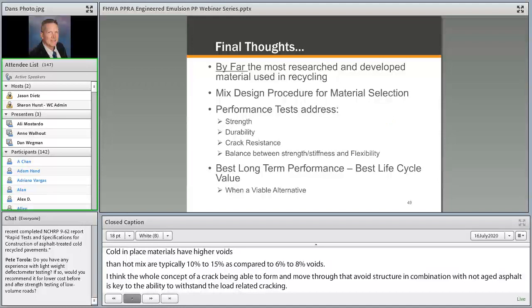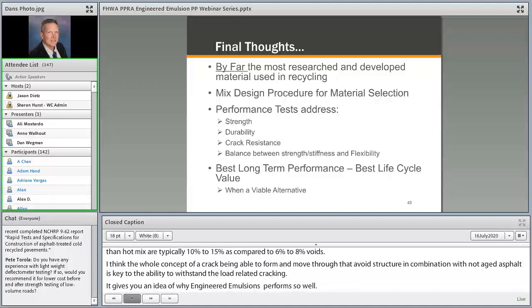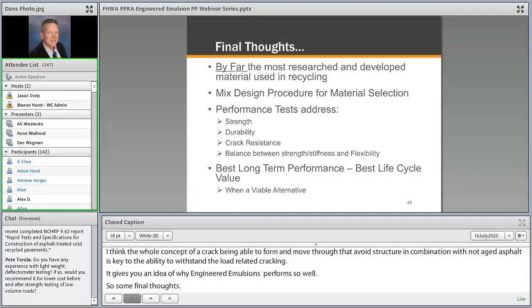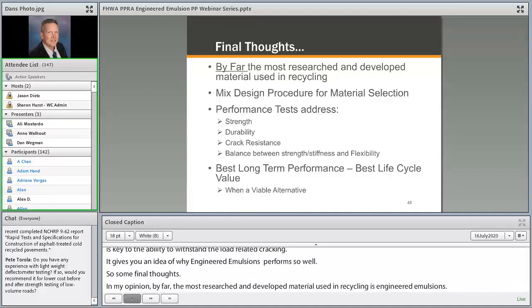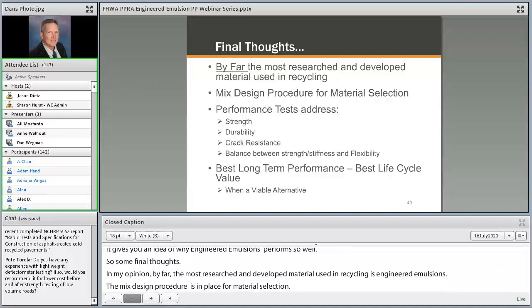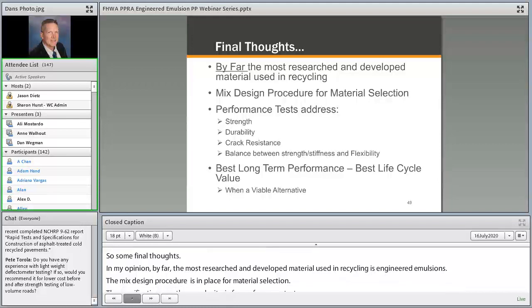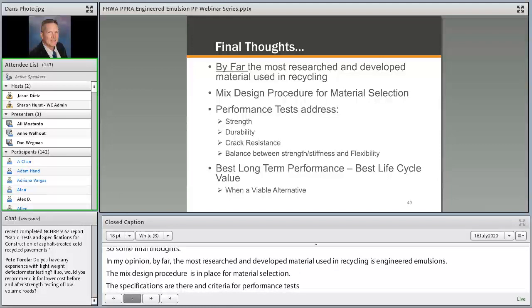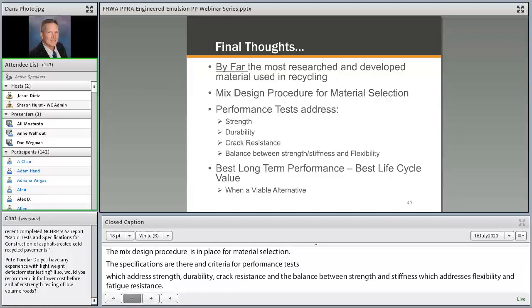So some final thoughts. In my opinion, by far the most researched and developed material used in recycling is engineered emulsions. The mix design procedure is in place for material selection. The specifications are there and criteria for performance tests which address strength, durability, crack resistance, and that balance between strength and stiffness, which addresses flexibility and fatigue resistance. It, again, in my opinion, provides the best long-term performance and best life cycle value, with the caveat that you've got to use it when it's a viable alternative. So that means doing your homework up front, understanding the materials that you're stabilizing, and applying it appropriately.